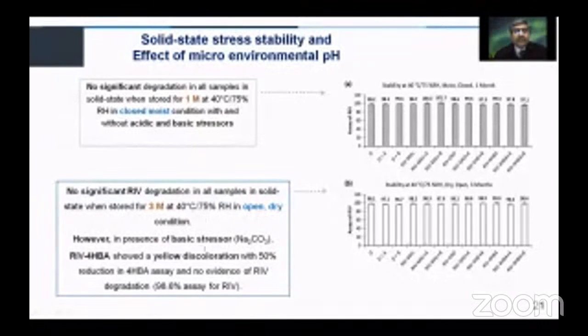However, in the presence of a basic stressor, that is sodium carbonate, the rivaroxaban 4-HBA co-crystal showed a yellow discoloration with 50% reduction in the assay of 4-HBA. However, there was no evidence of degradation of the rivaroxaban. Now, this leads to a very interesting scenario that although the rivaroxaban was not degrading, the coformer was degrading in one of the conditions. And if the coformer degrades, obviously there is going to be the disturbance of the crystal lattice, because the original co-crystal was formed with 4-HBA, while during the stability it has degraded into some other compound.